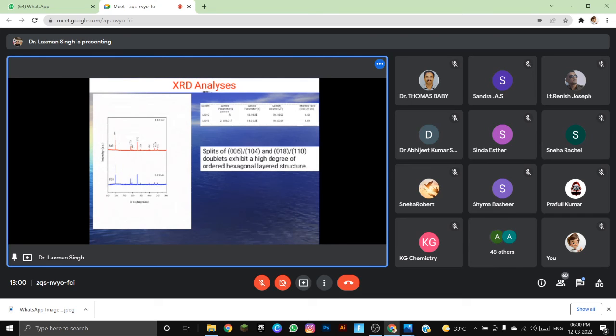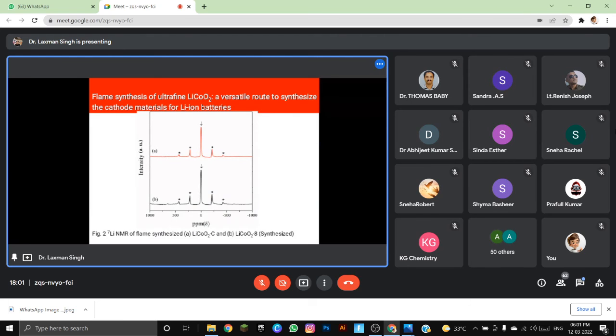For the comparison, we have taken the lithium cobalt oxide and commercialized lithium cobalt oxide from the market and compared them. This is the XRD of the lithium cobalt oxide, the commercialized one, LCO-C, and our lithium cobalt oxide, LCO-S. It gives the layered structure with high intensity XRD peaks.